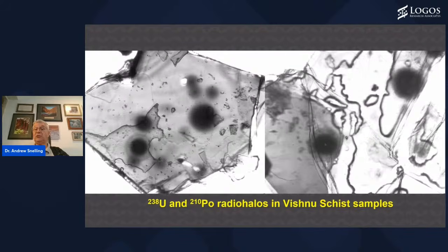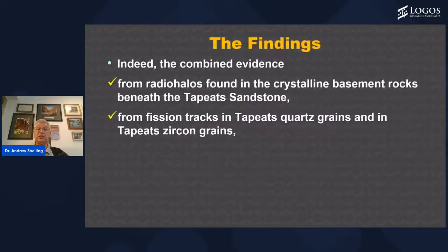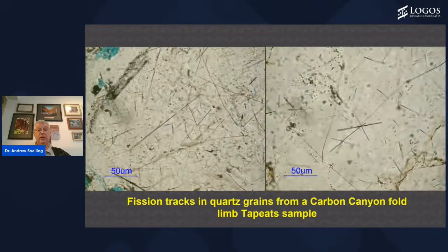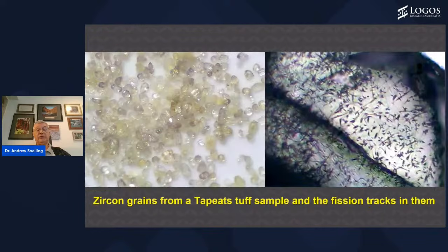And the fact that they're still observable means that since the radiohalos formed, the rock hasn't been subjected to temperatures above 150 degrees C. And then we find fission tracks in quartz grains within the Tapeats sandstone and within zircon grains within the Tapeats sandstone. Here are these fission tracks in samples from a limb zone Tapeats sandstone sample in the Carbon Canyon Fold. And here we see them from zircons collected from a tuff sample, a volcanic ash bed within the Tapeats sandstone, and the fission tracks within the zircons.